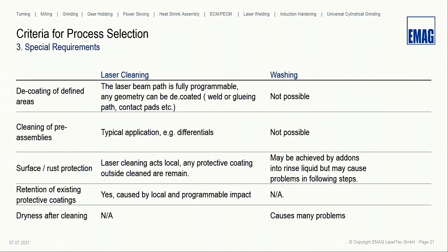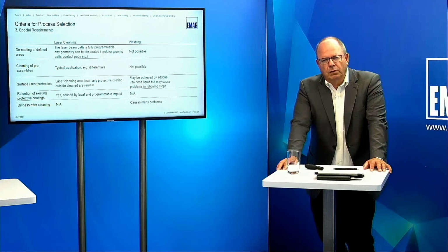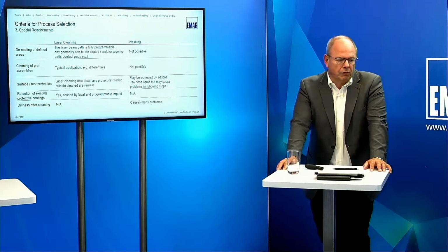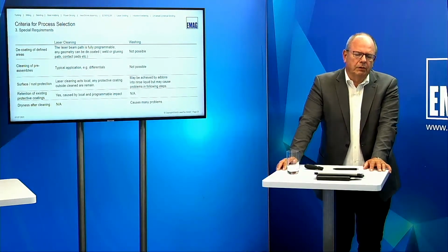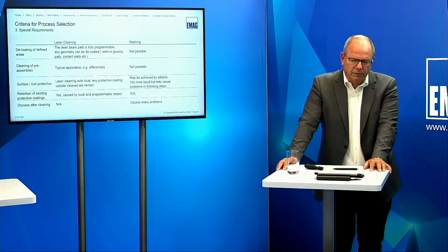We had a project where we had to clean an aluminum case for an electrical motor, and the final operation was a sealing operation. To remove the oxide layer, we removed it with laser cleaning, and it was a non-round geometry, so we had an XY coordinate system to clean the path for the sealant, the shape for the sealant. So this is a perfect application for laser cleaning. That is also true for pre-assembled components. You cannot wash them because you never would be able to clean and to dry them. So these are specific advantages of the cleaning process because it's so local.